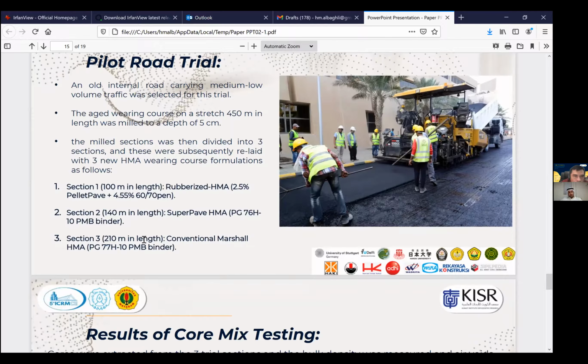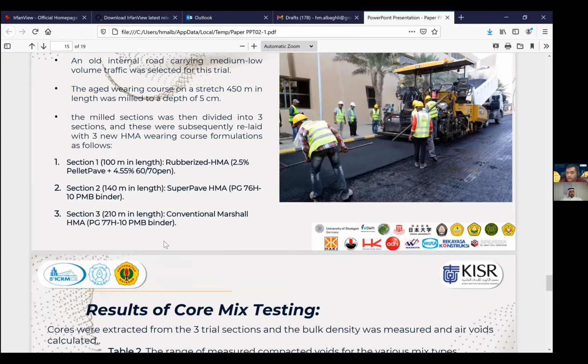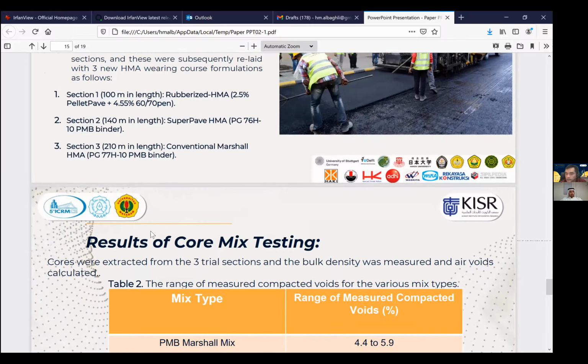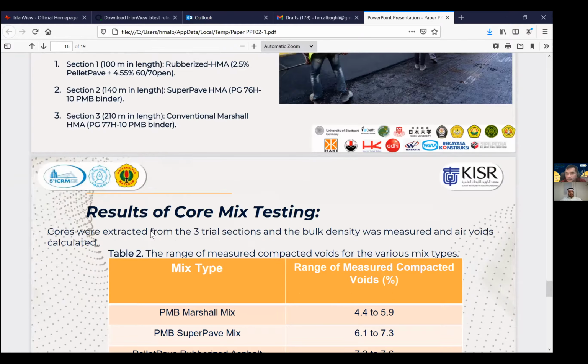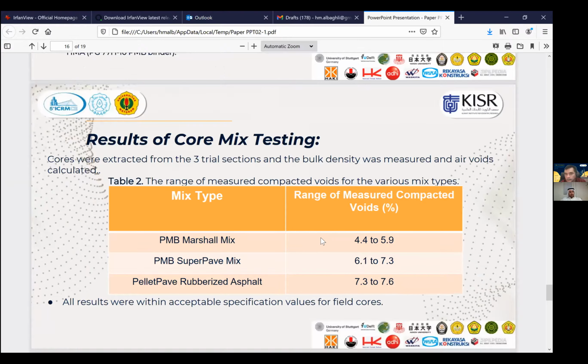210 meters in length. It had conventional Marshall hot mix asphalt with polymer modified bitumen. We extracted cores from each section to measure air voids and density. You can see the range of voids here for each section, and they all satisfy the specifications required.